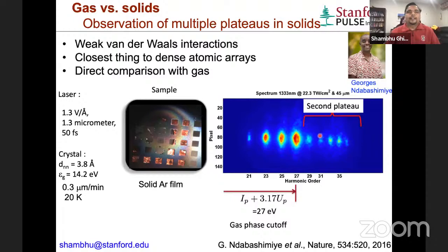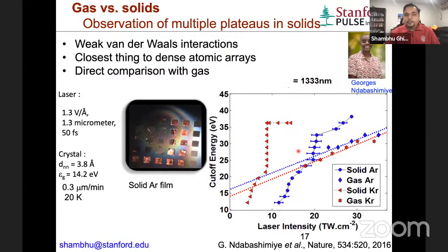So the idea was to compare the gas and solid in the same experimental conditions of the laser parameters. This is the high energy cutoff as a function of laser intensity. For the gas phase, we reproduce this linear scaling, but for solids, both for solid argon and krypton, there is something very different. And this second plateau really kicks in at certain peak intensities, actually two different intensities for different solids, depending on their ionization thresholds.